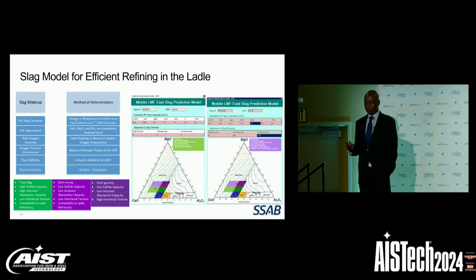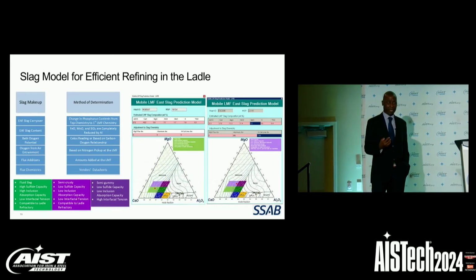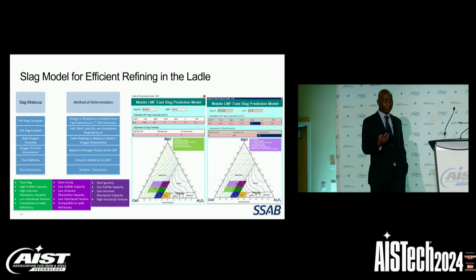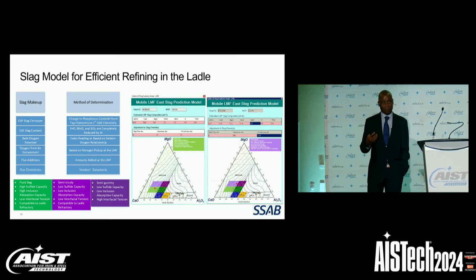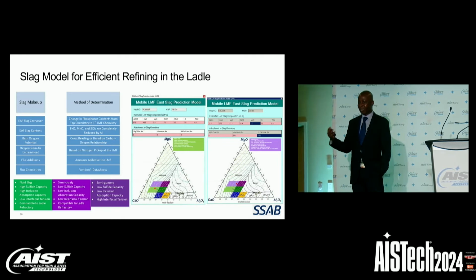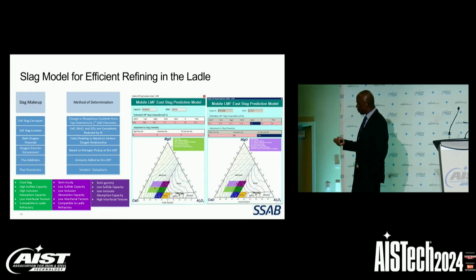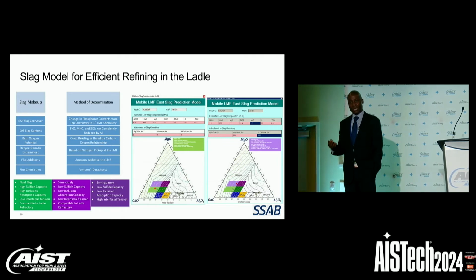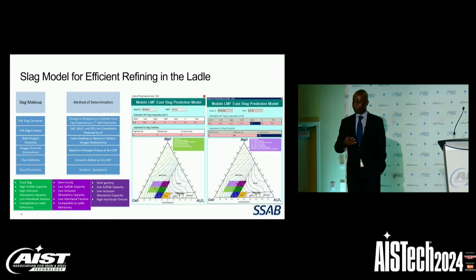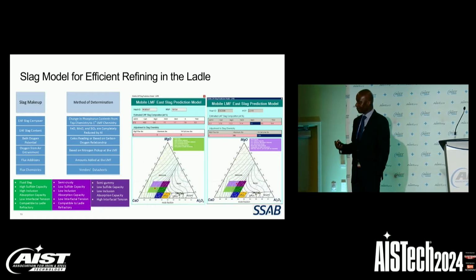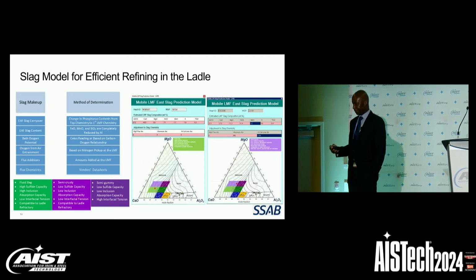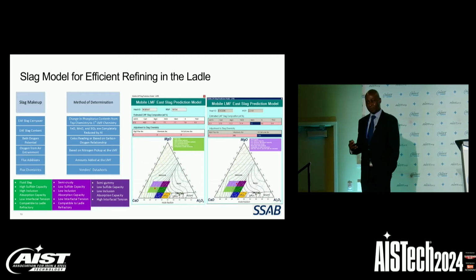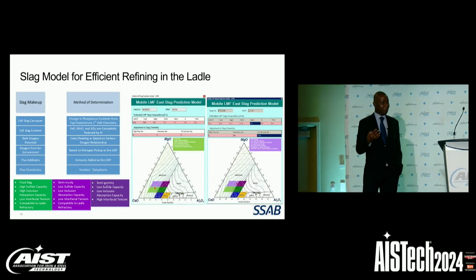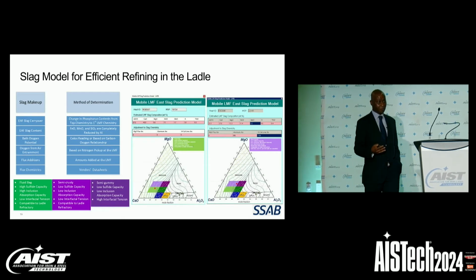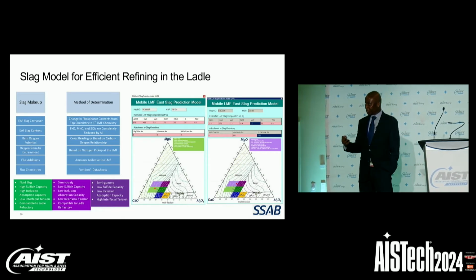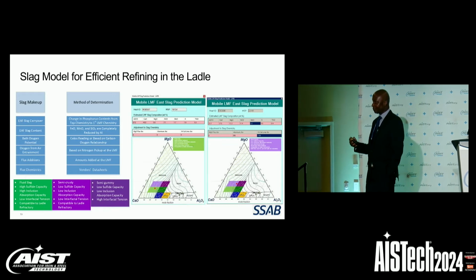For a model to work, we have to identify and quantify oxides from different sources that make up the slag. For example, the EAF slag carryover was calculated based on the phosphorus change from tap chemistry to the first LMF test. The alumina that is formed is calculated based on the oxygen potential of the liquid steel and the oxygen from the air that is entrained.